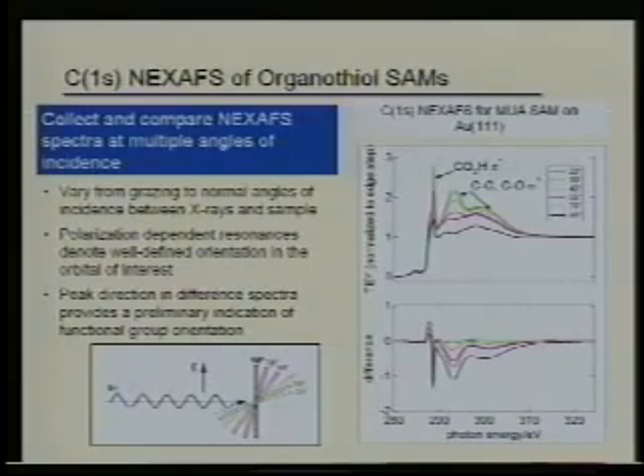The other thing to note here is that the thiol gold bond is fairly strong. This is the basis of some of your catalytic converters. So you have a platinum catalytic converter. Sulfur from your gas is actually getting trapped on these things. That's how bad gas gums up your catalytic converters.